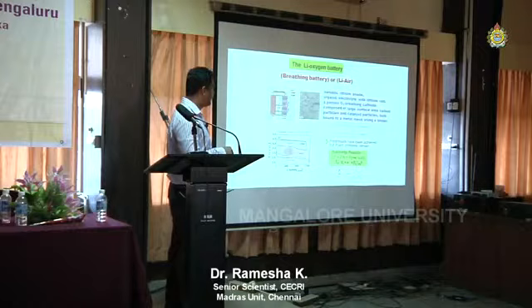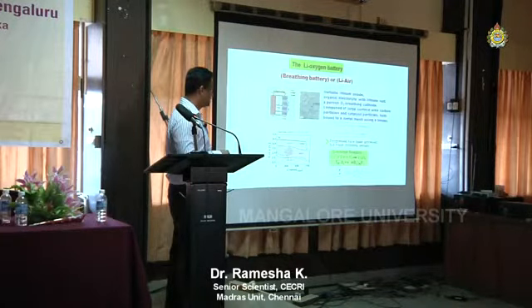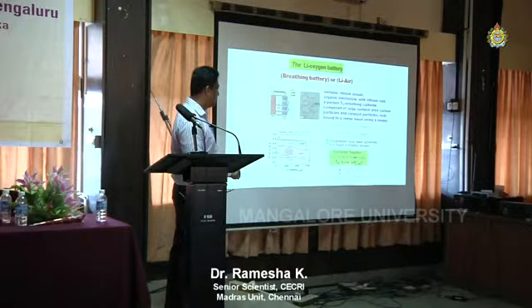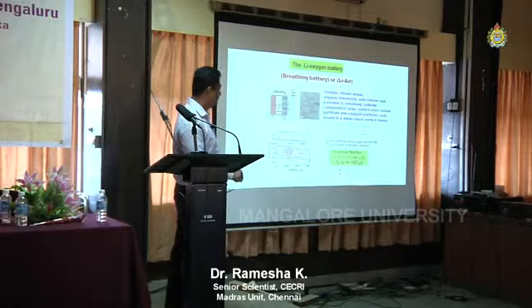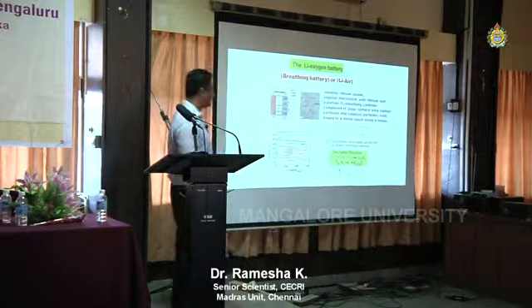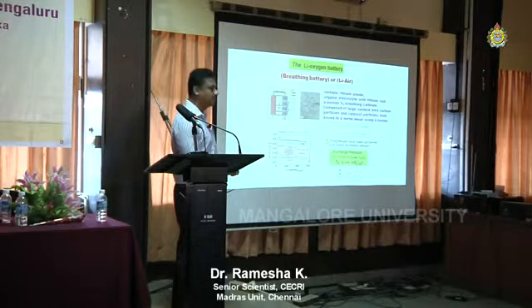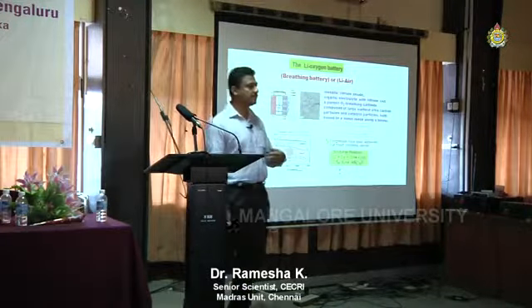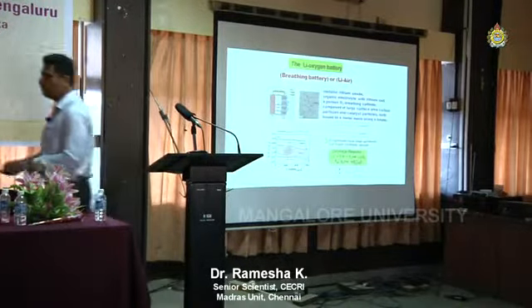I told you already what the issue here is. You have porous carbon, and then the catalyst should allow oxygen to come. The problem is that the electrolyte reacts with oxygen and decomposes. There are many other issues, like how to control the reaction. Many times we see that the forward reaction happens, Li2O2 formation happens, but the reverse doesn't happen. You need a very good catalyst to break the Li2O2 bond. The lithium oxygen bond is so strong.